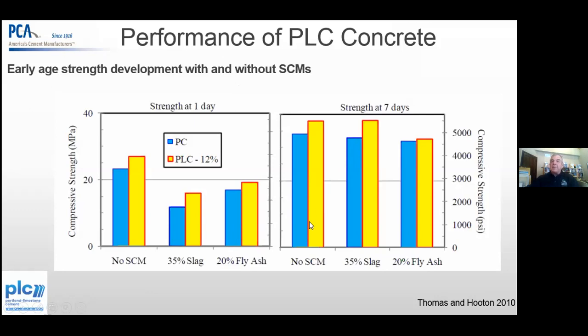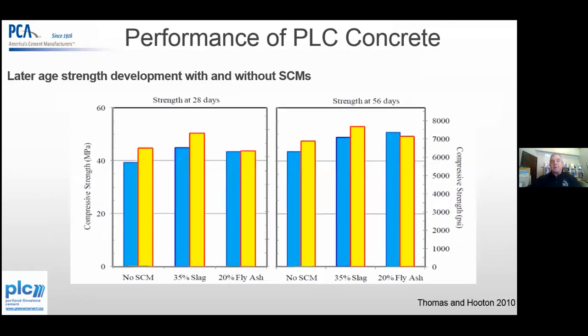I wouldn't hang my hat on the fact that you're going to get increased strengths all the time. My experience has been you get equal performance. So this is basically saying that you're getting equal performance. It just so happened in this particular test that the Portland limestone cement had better performance than the Portland cement, which you might find, but it should be equal. That's our goal. Our goal is to grind them and optimize the grinding, the intergrinding, and the gypsum addition to maximize our efficiencies in the mills, maximize the limestone content, but still get equal performance.